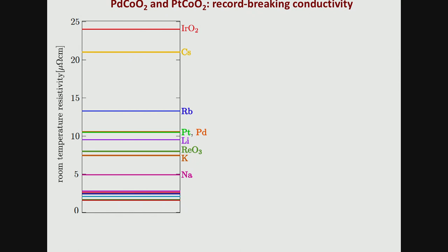So the reason we became interested in them comes from just looking at a chart of the room temperature resistivities of metals. So here we have, back to your textbook days, the alkali series of metals with their nearly spherical Fermi surfaces. These are all their resistivities. It turns out that the resistivity at room temperature of elemental platinum and elemental palladium are rather similar. There are a couple of the most famous highly conducting oxides put in here.